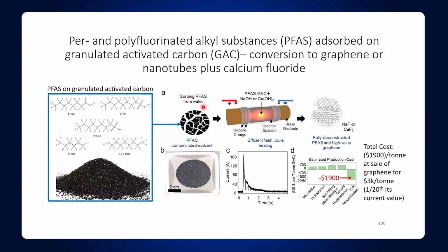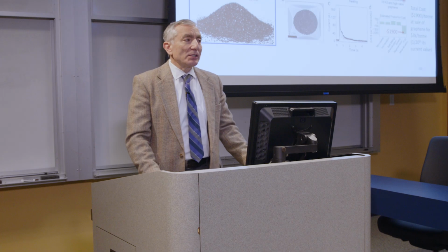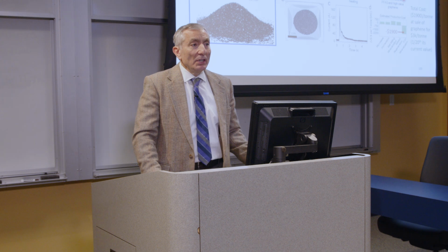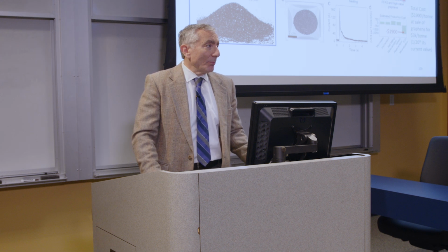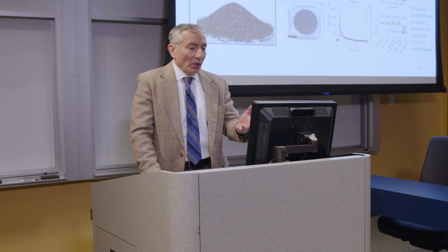Well, we've shown that we can take the PFAS that's adsorbed on carbon, we put it in a sealed system, so there's double O-ring seals. We apply a voltage, a high current, high voltage, and it turns into graphene. And we add into this calcium hydroxide or sodium hydroxide. If you add in calcium hydroxide, when it flashes, it turns into calcium fluoride. Calcium fluoride is the natural mineralized form of fluorine in the environment. So where do you find fluorine? You find it as calcium fluoride. It's a very stable compound, not very water soluble. Has some water solubility, but not very much. And it's non-toxic. So we turn it back into the natural material along with graphene.